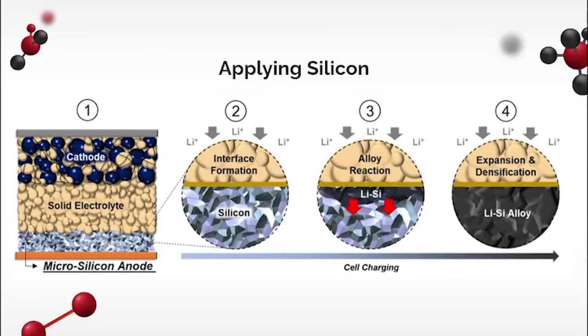UCSD has also addressed two key drawbacks that silicon has had. Silicon expands to approximately 400% when reacting with lithium, which along with reactions between the solid electrolyte interface and silicon cause quick degradation. UCSD has opted to use microsilicon as it is able to tolerate volumetric expansion and a solid-state electrolyte to avoid premature degradation. Researchers formed a stable and passivating solid electrolyte interface layer by using solid-state electrolytes instead of liquid electrolytes in an all-solid-state battery. They have incorporated a 99.9 weight% microsilicon electrode, using it in micro-Si, SSE, lithium nickel cobalt manganese oxide, NCM811 cells to enhance the interfacial stability.